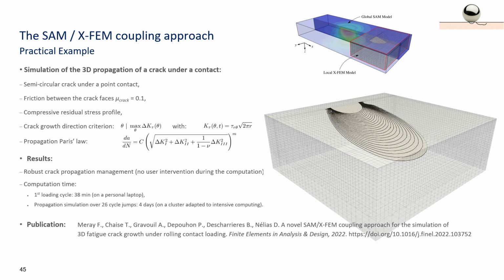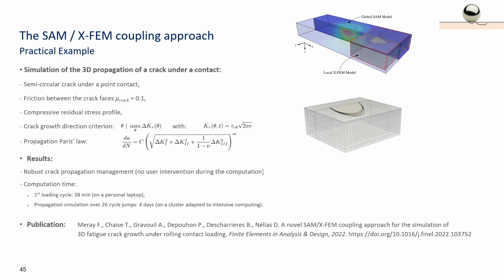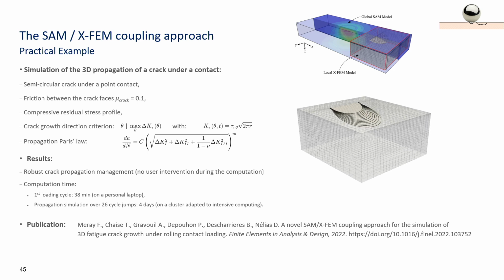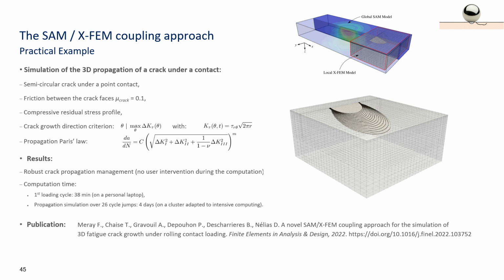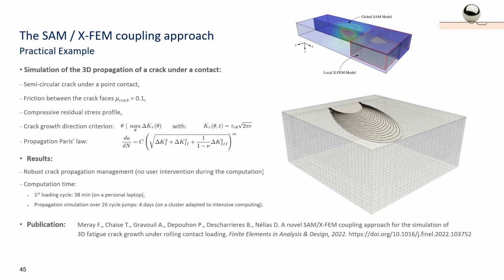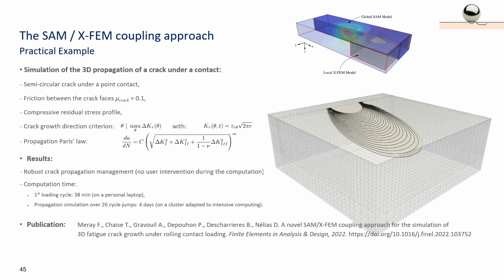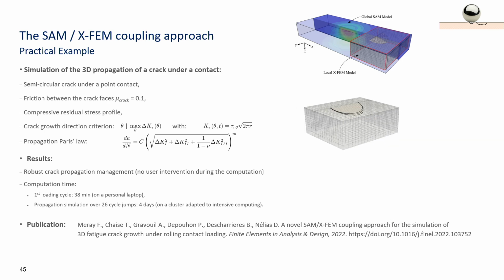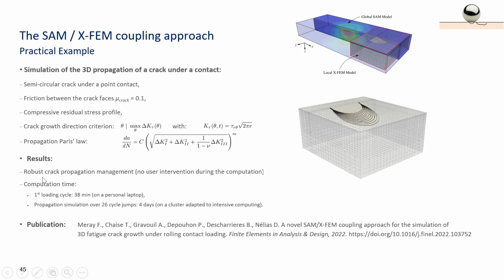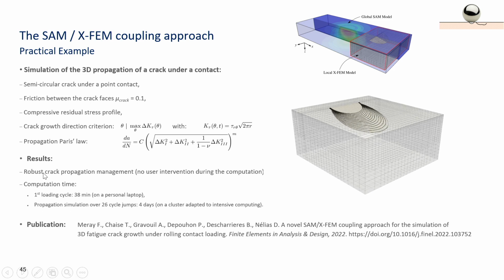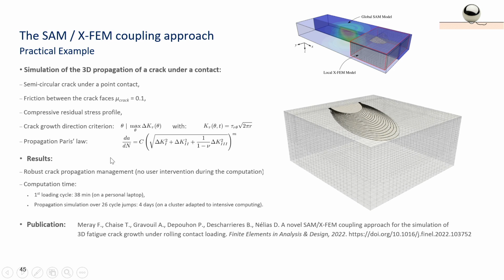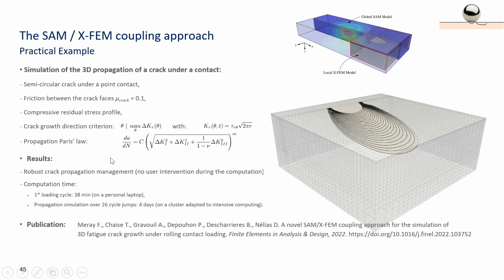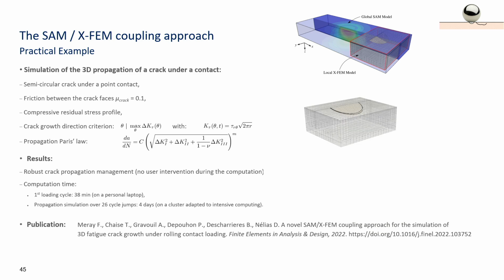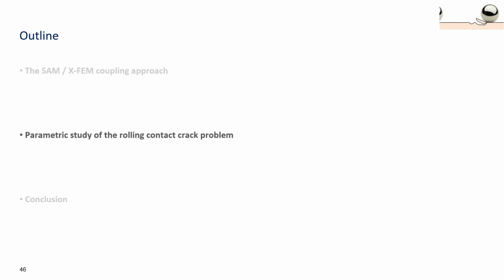And now, when you have the model, you can modify the parameters of the study. You can modify the initial inclination of the crack, for example. You can modify the size of the contact. You can introduce residual stresses and so on. Okay, and also the approach is very robust. You have nothing to do. You launch the simulation and you have the results. Everything is in a paper which is given below.